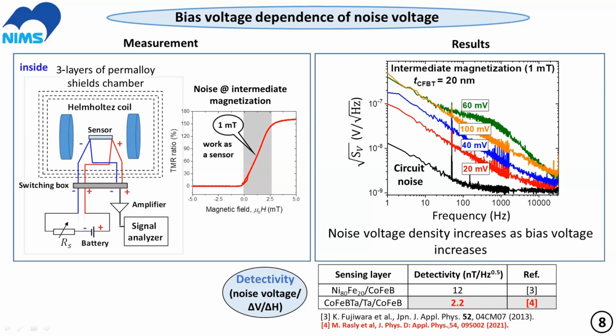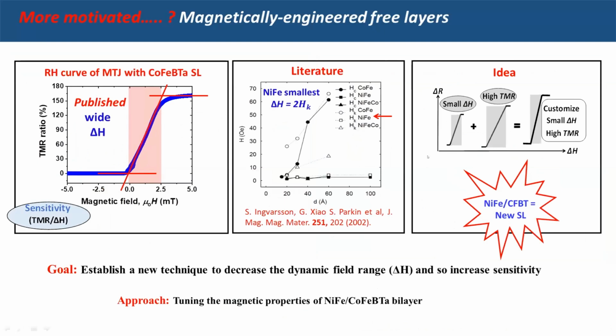After we achieved this in 2021, we became very motivated and planned our next step. Actually, as you can see here, this is our hysteresis-free curve. But if you look deeply at this linear transfer curve, you will observe that delta H is a little bit wide. So the point is, if we can successfully decrease this delta H, which determines how much sensitivity you have, for example from 2.5 to 1.5, then the sensitivity starts to increase.